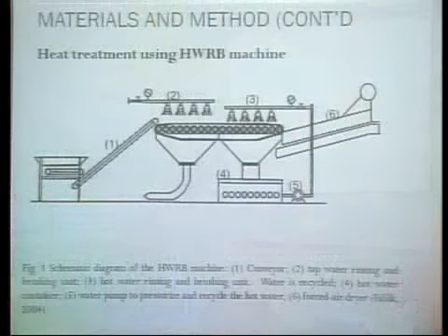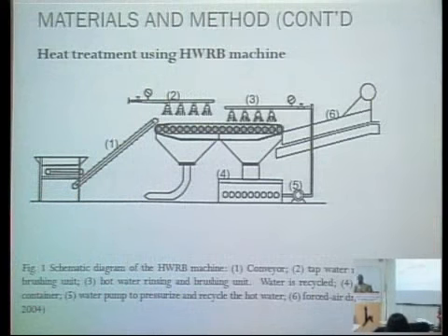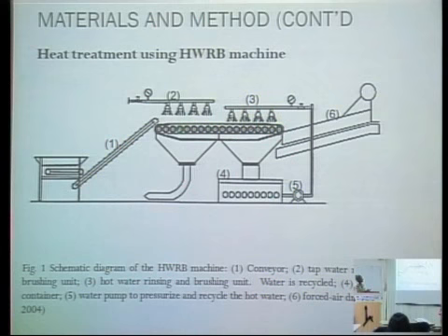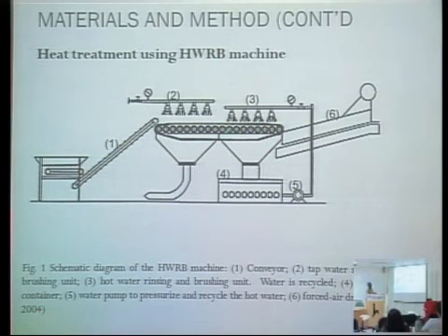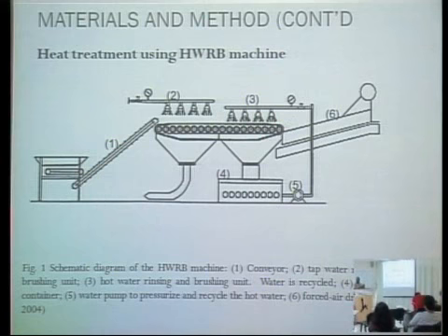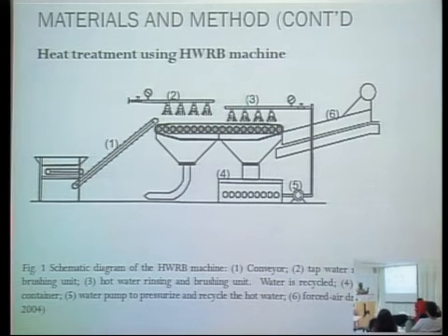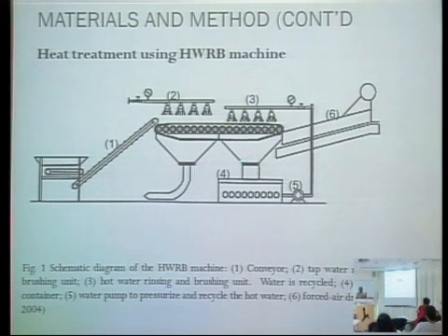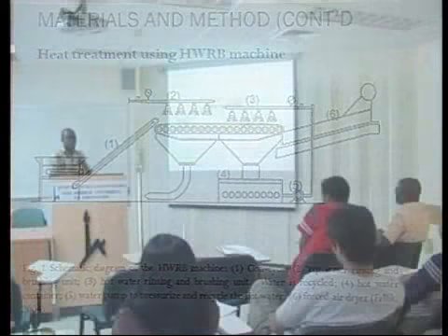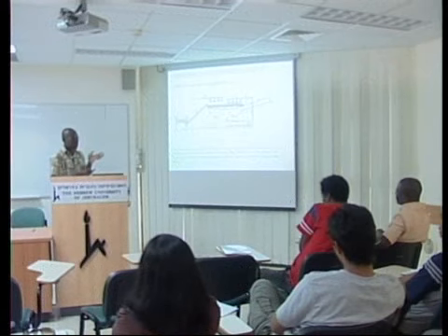Okay. I'll explain it using this machine. The calyxes were removed because when the fruits are being rolled on the brushes over here, we don't want a situation whereby they get stuck in the brushes. Or better still, because the calyx is sharp and pointed, if the fruits roll on the brushes, there's a tendency that the calyxes can even destroy the skin of the other fruits. So to avoid that, that is why we remove the fruit calyxes for this treatment.